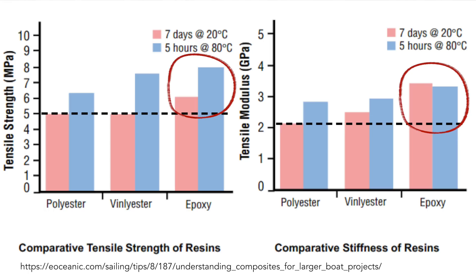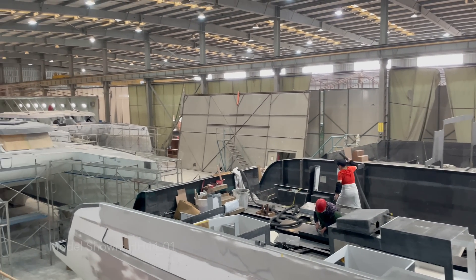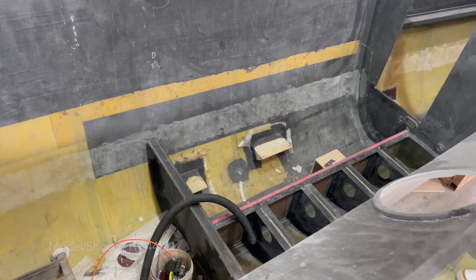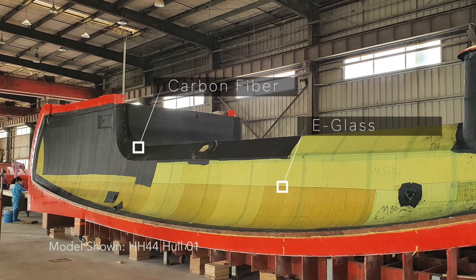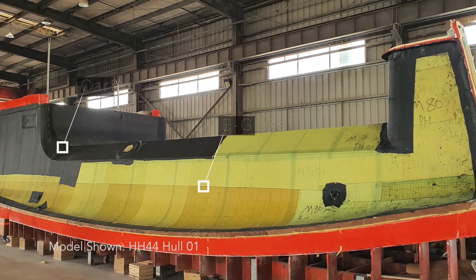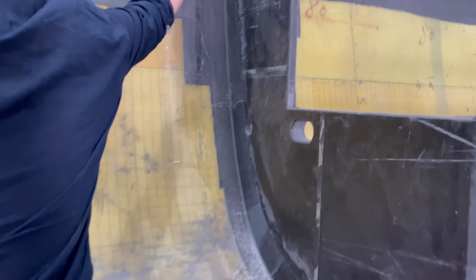The reinforcing that makes the boats so rigid and stiff is the carbon reinforcement. We have massive carbon in all the bulkheads, all the beams, all the frames — everything that is basically the skeleton of the boat is carbon fibre with epoxy, all infused. The plating on the outside of the hull and deck is done with e-glass, again epoxy infused foam construction — for cost saving, but also because there's no performance gain in that area. There is, however, a lot of carbon still in high-load areas such as where the daggerboards and rudders attach to the hull, and at the chain plates.